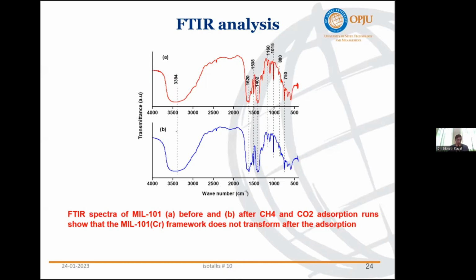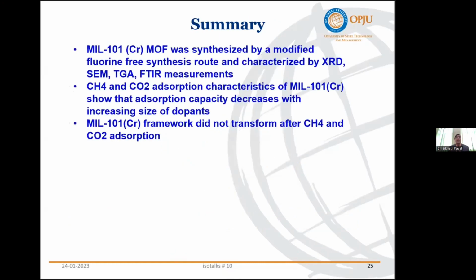Okay, so let me summarize this whole presentation. Basically, this MIL-101 chromium MOF was synthesized by a modified fluorine-free synthesis route, and characterized by XRD, SEM, TGA, FTIR measurements. Methane and CO2 adsorption characteristics show that the adsorption capacity decreases with increasing size of dopants, and the original parent MOF structure does not transform after methane and CO2 adsorption. So these are the main conclusions I can draw from my presentation today.